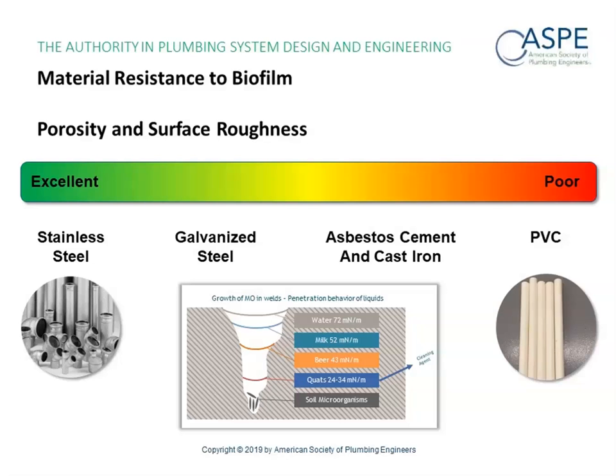Second to that, you have asbestos cement and cast iron. Rating somewhere about there is galvanized steel, and then we know that stainless steel 316 in particular rates excellent in terms of the resistance to biofilm formation. And that has to do a lot with the metallurgy and the fact that it just does not like to grow. Biofilm does not like to grow on stainless steel.